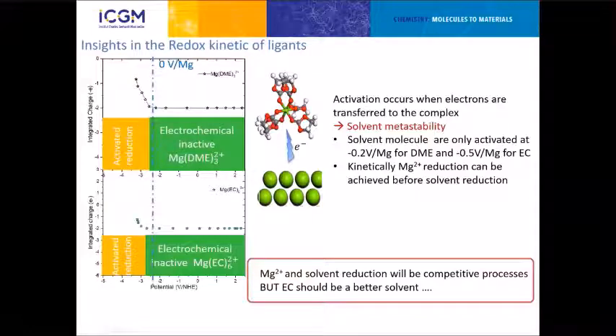For ethylene carbonate, it's about the same, but ethylene carbonate should be quite a bit better. The electroinactive zone is slightly larger around magnesium, so ethylene carbonate should be better. But of course, ethylene carbonate is not better, so there's something more to understand.